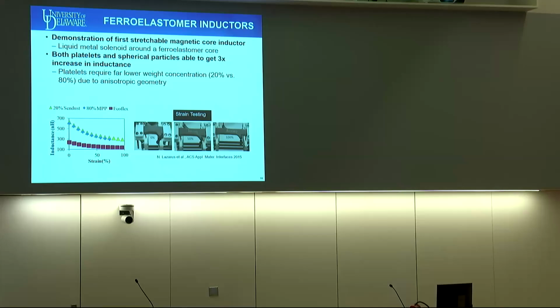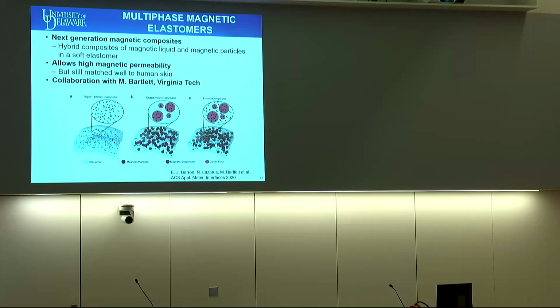You might ask why we don't then just increase the amount of magnetic material up to 80%. The reason is that it also has a bigger effect on the mechanical properties and the molding behavior. Essentially, 20% was the maximum we could effectively do for the material. However, because of this stiffness change, this was not very desirable for making a truly soft robot. And so we were interested in looking at whether there are ways to get that magnetic response without a resulting increase in stiffness.